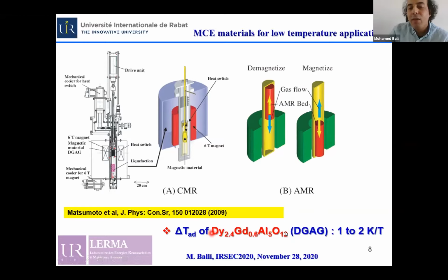So in the developed magnetic refrigerator, a magnetocaloric garnet, shown here, is used in an AMR cycle to achieve the refrigeration process. However, as you can see here, this family of garnets exhibits moderate magnetocaloric properties, particularly in terms of the adiabatic temperature change that reaches only 1 to 2 Kelvin under a magnetic field change of 1 Tesla. So in this context, it is necessary to search for more advanced and performant materials for cryogenic applications.